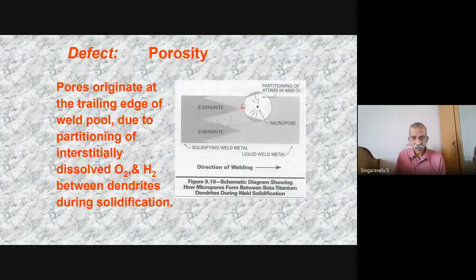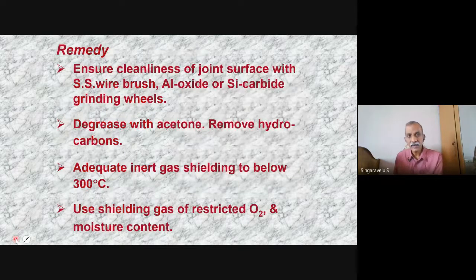So normally pores originate at the trailing edge of the weld pool, due to the partitioning effect of the interstitial between the dissolved oxygen and hydrogen. When gas pores are generated in between, they get blocked. That's why it is called the interstitially dissolved effect. Right? What's the remedy then? Cleanliness, cleanliness, cleanliness is the only solution.